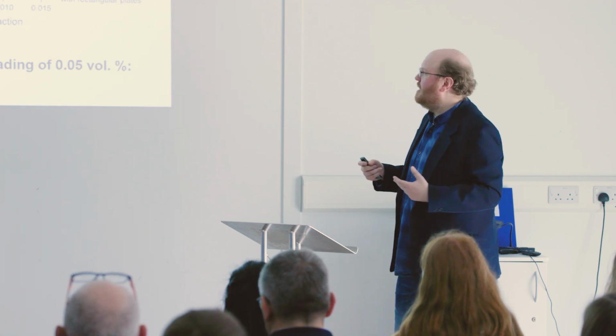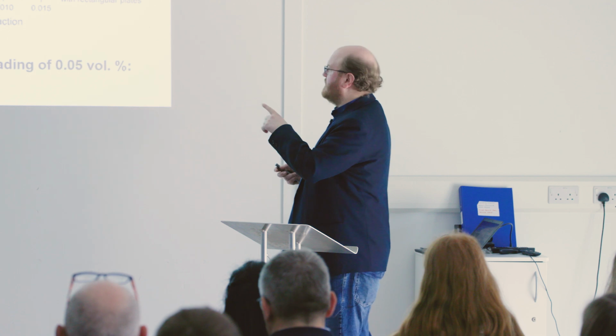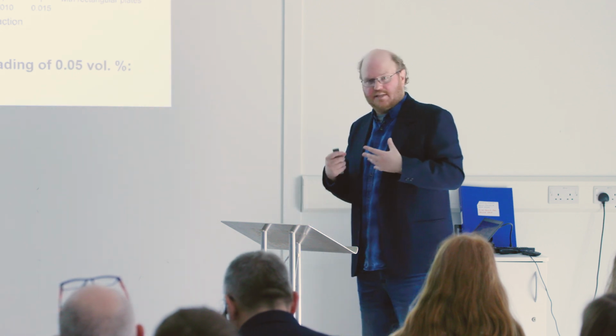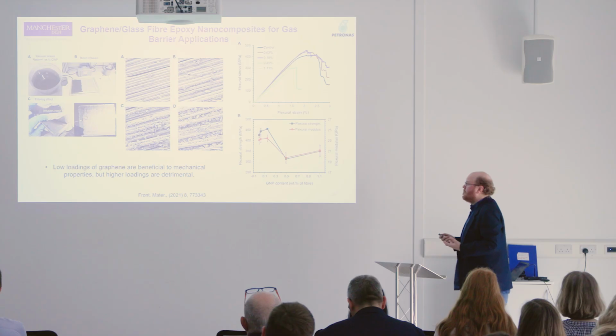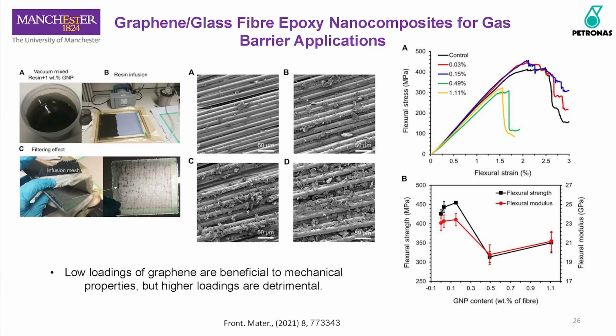And that's because you've got this added tortuosity that the gas molecules can't pass straight through. They take much longer because they run into these flakes that are impermeable. So by adding only a very small amount of material, you can sometimes get these barrier properties that you might not have expected, which is quite nice for a lot of different applications. You can also look at, say, the mechanical applications of this.